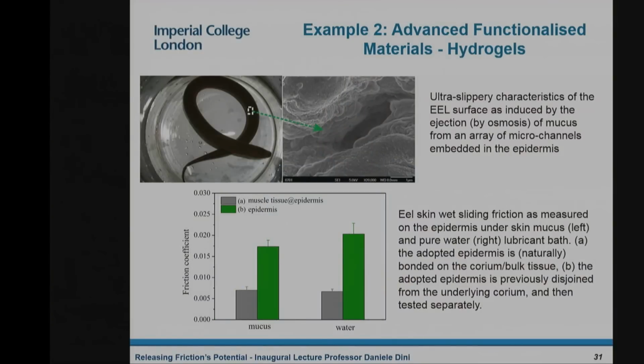Now, the funkier application comes from my colleagues in China who wanted to do something biomimetic and decided that they wanted to look at eels. And from experimental evidence, squashing the eel and doing something to it, they worked out that the very slippery surface on the eels is due to the presence of mucus, which is coming out by osmosis from pores. And inspired by that, they developed something similar.